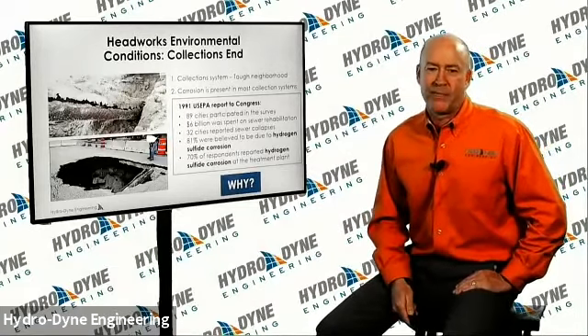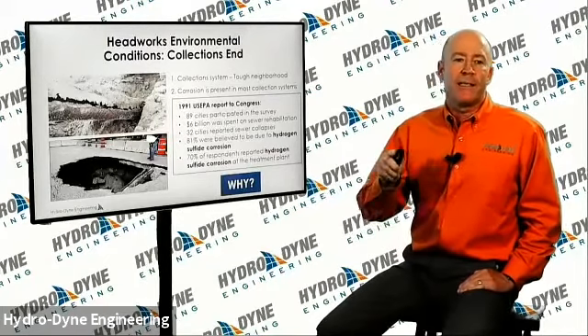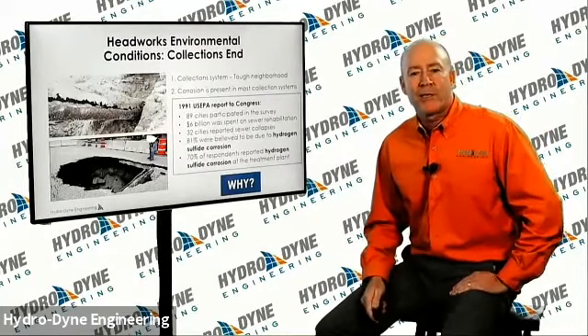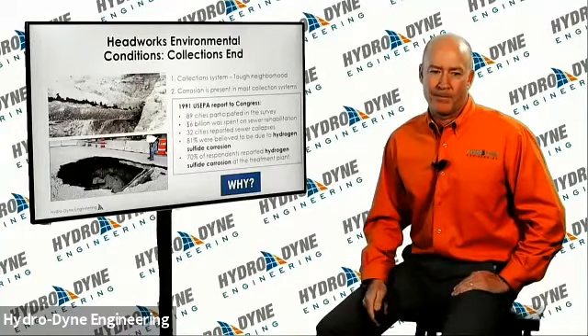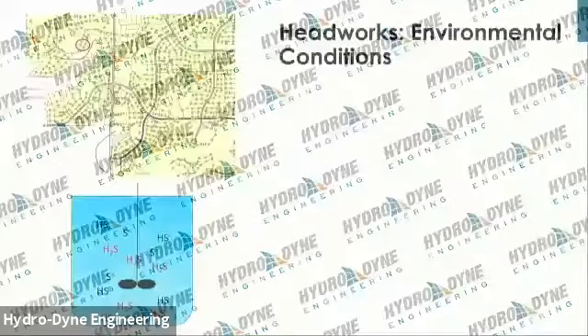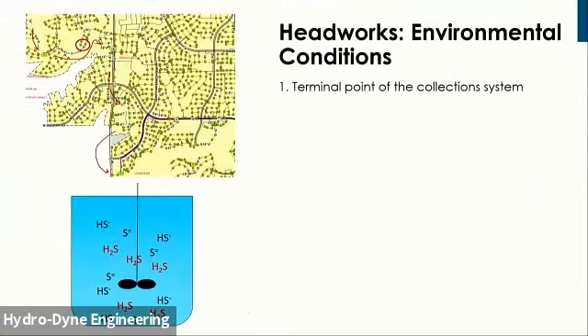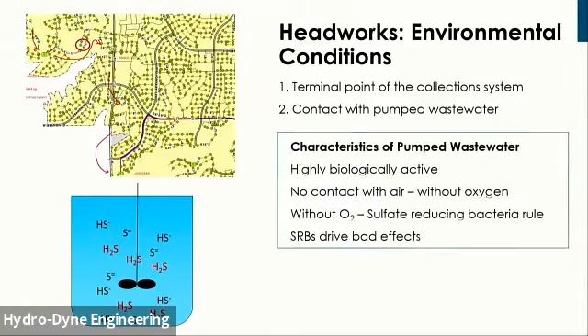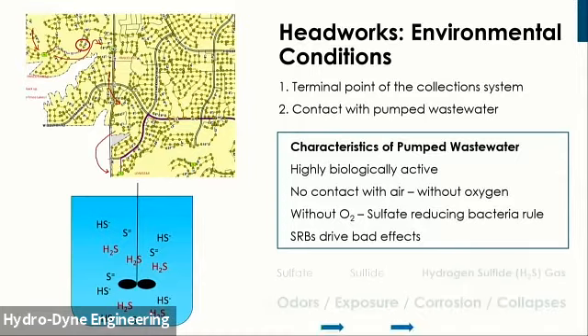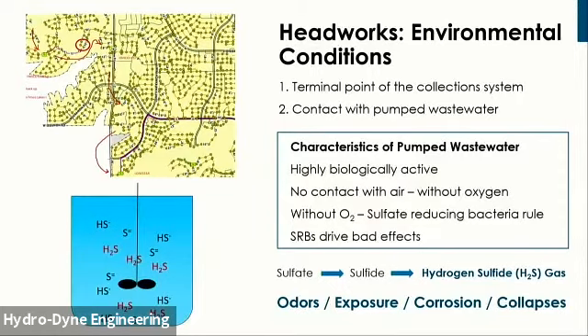So this is something that's pretty widespread, and you may ask why. There are two sources that I wanted to talk about that directly impact Headworks equipment: biogenic corrosion and corrosion driven by high chloride content. First, biogenic corrosion. We're going to go back to the collection system, and as the Headworks, we are the terminal point of a collection system. And you noticed I talked about pumped wastewater. Pumped wastewater is highly biologically active. It has no contact with air typically. So without oxygen, sulfate-reducing bacteria that reside in the system can take over. And the sulfate reducers can drive bad effects. They take the sulfate, turn it into sulfide, and then turn that into hydrogen sulfide gas.